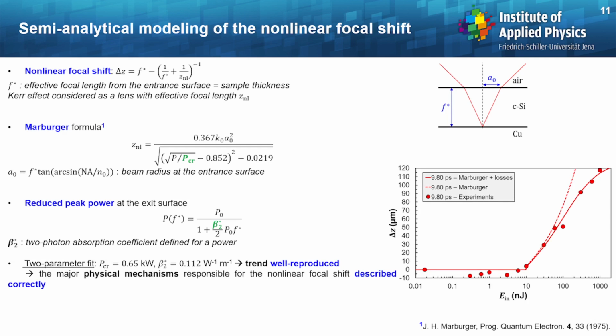Okay, so how does it compare with the experiments? Well, delta Z here is shown as a function of the input pulse energy. With this two-parameter fit, we can see that the trends are very well reproduced by this solid line here. Noteworthy, when the nonlinear losses are not accounted for here, then we have simply the Marburger formula, which overestimates the experimental data. So this fit here means that the major physical mechanisms that are responsible for the nonlinear focal shift are